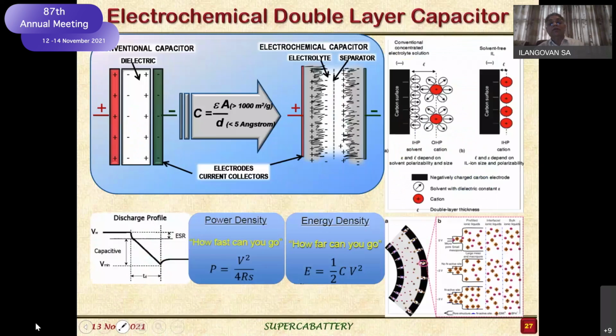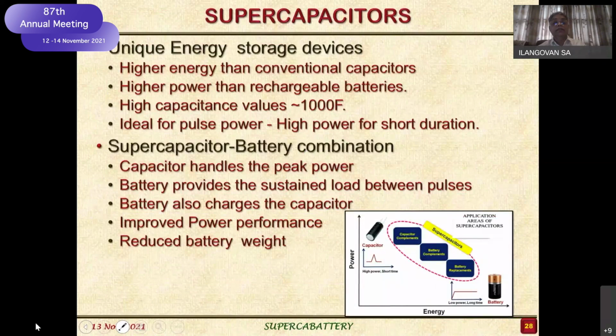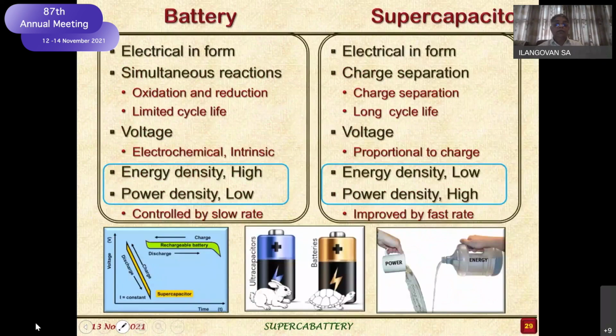Yes. The concept of the capacitor, the electrochemical double layer capacitance, was well known, but of late only it has picked up. We took that up and developed it, and a lot of advantages were there. 1000 farad technology was developed, but the problem is that the energy density is high but the power is low in the battery. The supercapacitor is the other way: energy density is very low but power density is high. It is able to sustain the voltage, but a supercapacitor will not be able to sustain the voltage for a long duration. I can only use peak. That is the kind of thing.